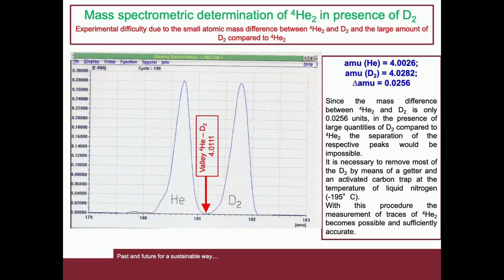Since the mass difference between helium-4 and deuterium is only 0.0256 units, in the presence of large quantities of deuterium compared to helium-4, the separation of the respective peaks would be impossible. It's necessary to remove most of the deuterium by means of a getter and an activated carbon trap at the temperature of liquid nitrogen. With this procedure, the measurement of traces of helium-4 becomes possible and sufficiently accurate.